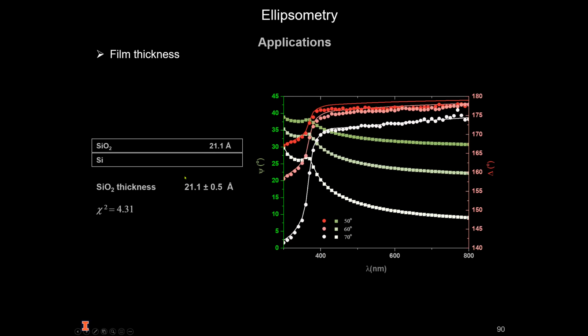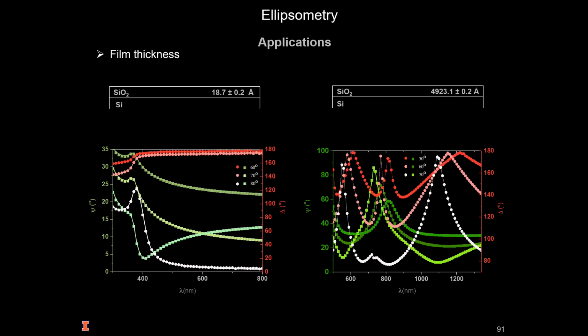In this case, we used XPS and X-ray reflectivity to corroborate our results from ellipsometry, so those are two very commonly used complementary techniques to ellipsometry. The range of thicknesses that can be measured by ellipsometry goes from less than a monolayer, basically, to a few microns of thickness, making ellipsometry one of the most powerful techniques in that aspect.